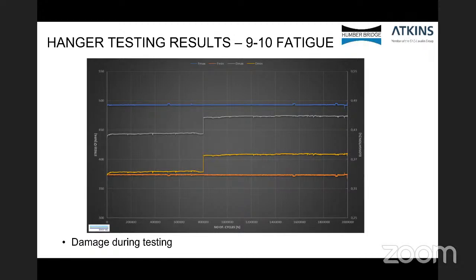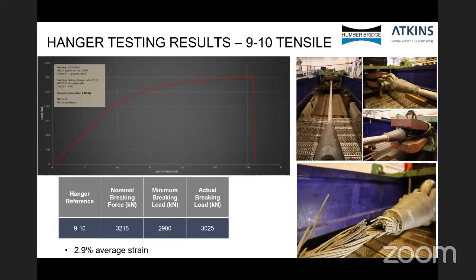If you look at the next slide, please. Tensile strength results after the fatigue testing, again, very similar results, 3025 with a 2.9% average strain. The failure was at the top end of the hangars, and you can see the breakage close to the hanger, close to the socket. Okay, next slide, please.